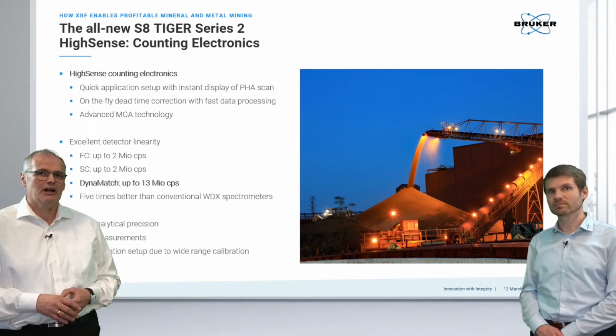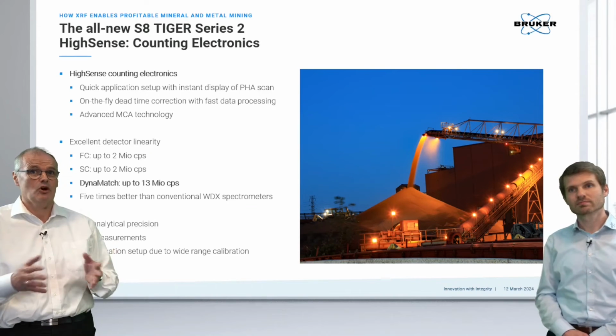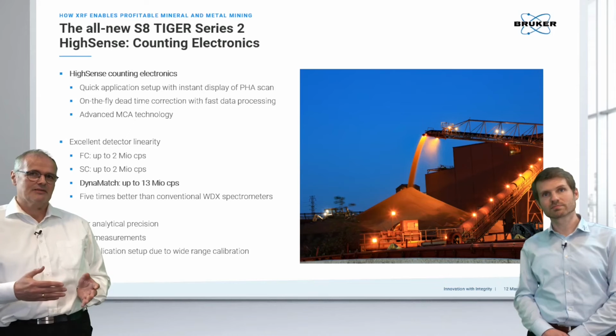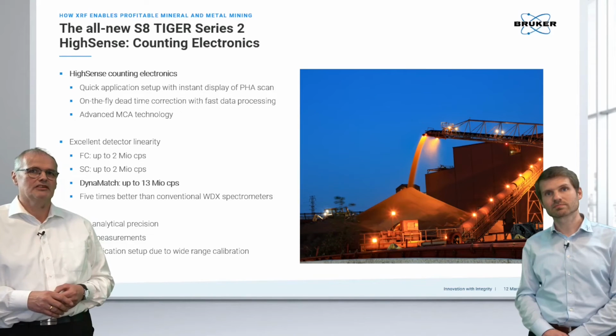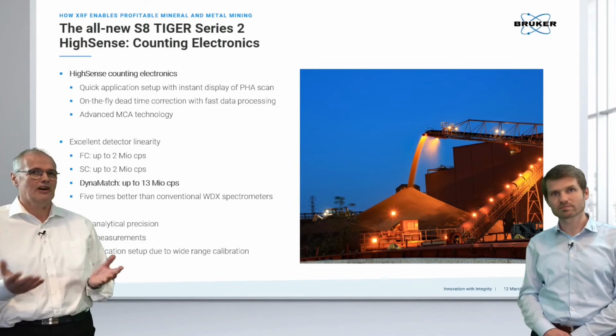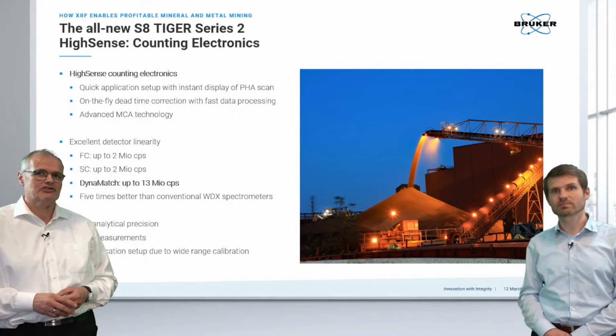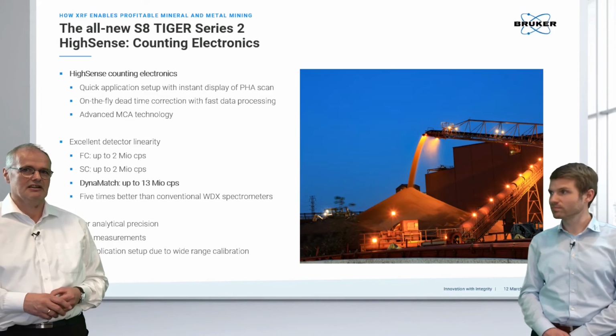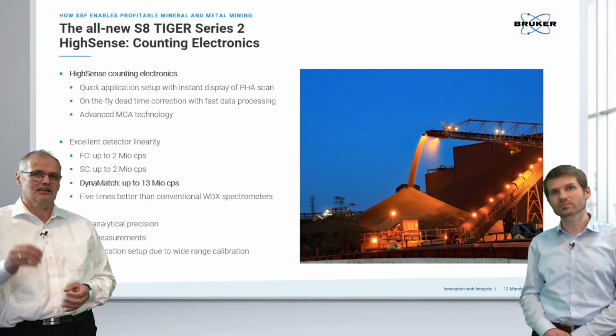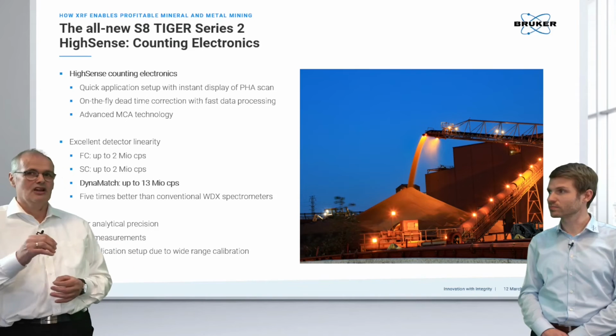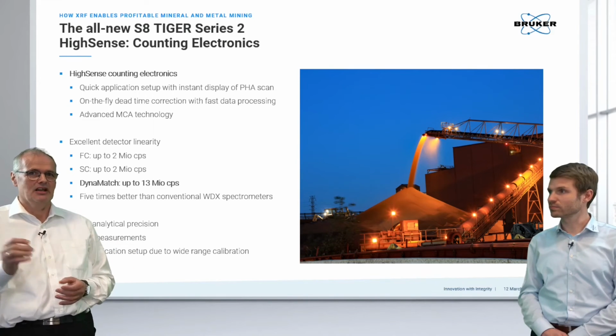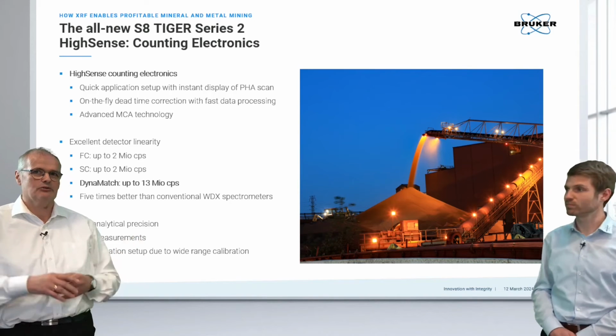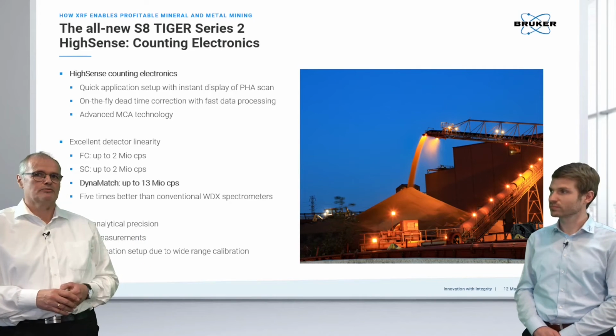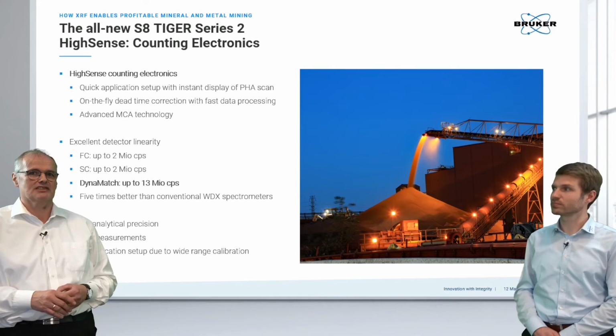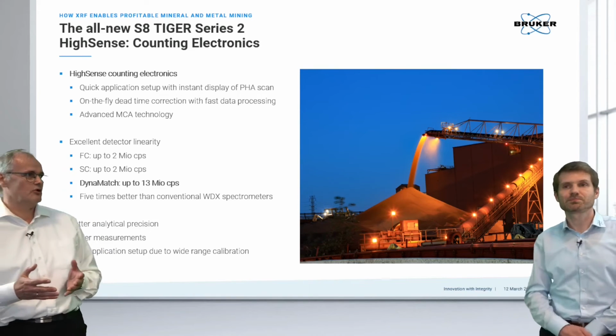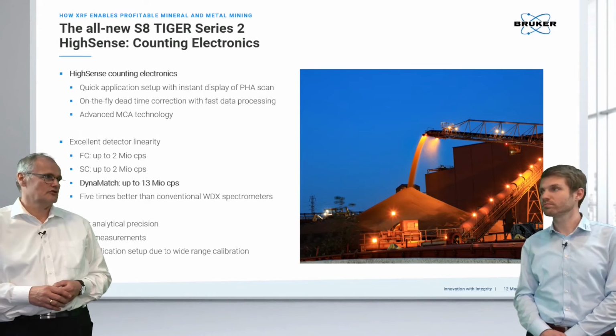And the trick is that we have a multi-channel analyzer, which on the one hand sums up all the counts very fast. And this helps us to achieve count rates up to 2 million for the flow counter and scintillation counter without any correction. And when we apply the Dynamatch technology, we can go up to 13 million counts per second. The interesting thing is that those count rates are not for the entire spectrum, but we are counting one element at a time. And so when we are able to analyze iron with a count rate of 2 million counts per second, we are pretty fast and getting very precise results. This is especially important when we go to process control or grade control.